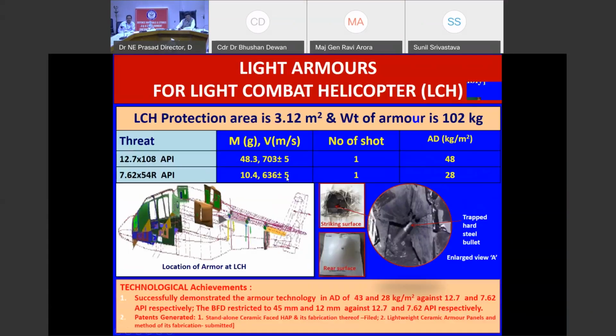Next one. Then we have light armors developed by DMSRDE. As I said, it requires a single parameter called areal density. You can change the material composition, modular structures, the composites, and they are extremely important when the weight of the structure for any particular system is important. But though it is aeronautical, the light combat helicopter is not as critical as a personal body armor. Let me tell you, the bulletproof jacket requires an areal density of equal thickness around 22 to 27, according to the latest Indian standard, whereas the equivalent one for LCH is only 30 plus or even 28 plus.